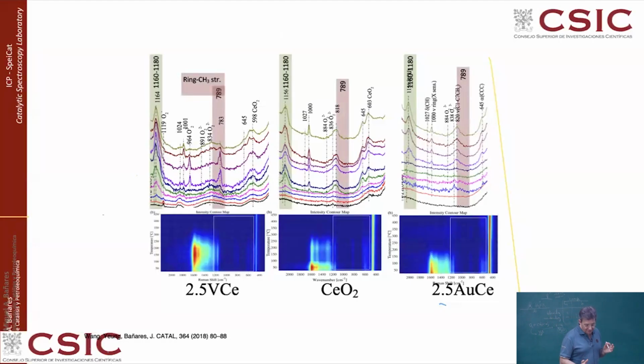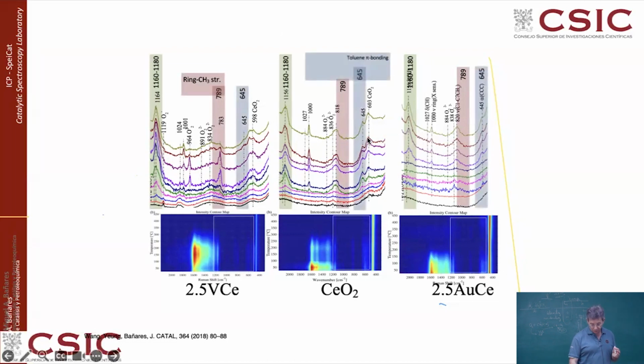So that is a vibration that is not observed from the others, because the other two catalysts present this other weak band over here, which is associated with the pi bonding of the aromatic ring, so that the aromatic ring is basically adsorbing at the surface of the catalyst. And if the aromatic ring is adsorbing at the surface of the catalyst, you are destabilizing this aromatic ring, which is already telling you that the most difficult part to burn in the toluene molecule is the aromatic ring, because this is very stable, and this pi bonding is already destabilizing it. So it makes sense that ceria and gold ceria are much more efficient burning toluene. And on the other hand, with the binding that you observe on vanadium ceria, the aromatic ring is there, which makes it more stable.